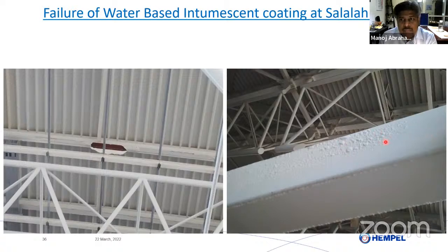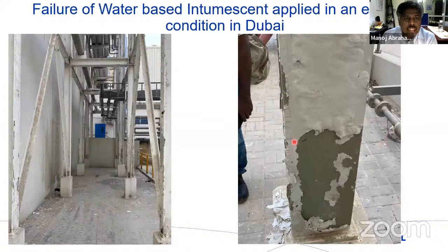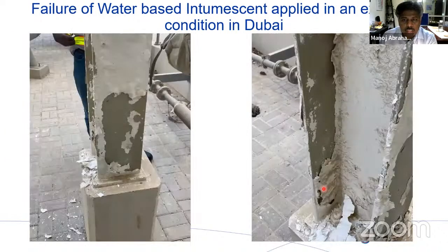A recent inquiry that we got in Dubai. Again, they applied water-based intumescent. And you can see there is no corrosion. The primer still seems okay. But you can see that the water-based intumescent starts to fall off. A closer shot: you can see that it tends to fall. So it is very important that we select the right product for the right environment.